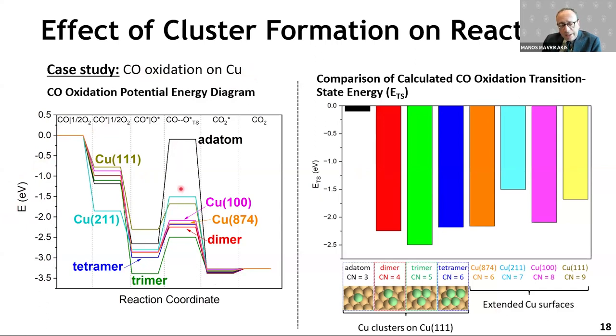The lower the energy level in this cell is, the more reactive the active site will be. We monitor this transition state energy on the right-hand side plot. And you can see here the transition state energy of copper 111, 100, 211, these are all standard facets people have been considering to explain reactivity. The monomer has a very high transition state energy. It's a bad catalyst. The dimer is good. In fact, the trimer, this green bar, is impressively good. If you compare a trimer of copper for CO oxidation, it should have about 12 orders of magnitude higher reaction rate at room temperature. So it's an enormous difference. One of these guys can do the job of 10 to the 12th of the most stable sites. So having trimers could clearly dominate reactivity.